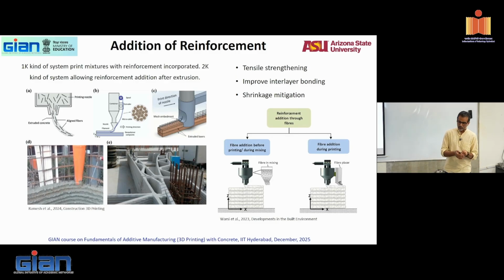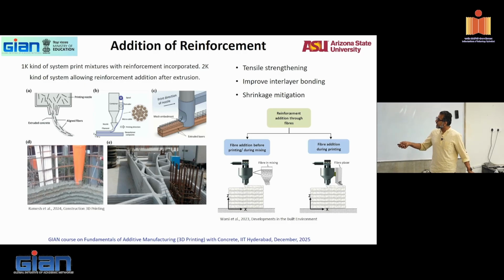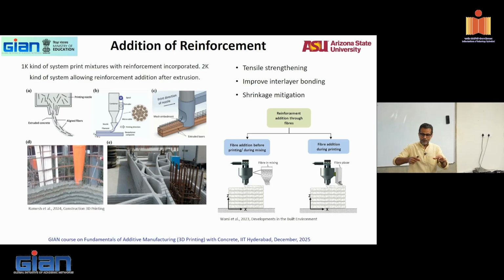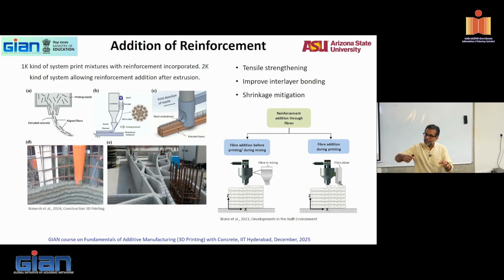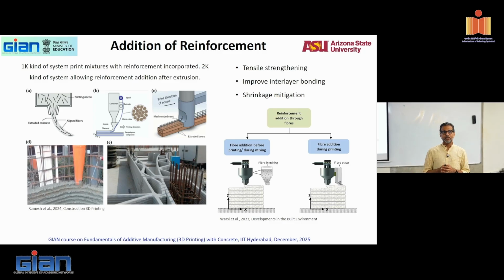And if you look at the random orientation of fibers added, as you print you see these fibers aligning along the direction of printing. The fibers will start to align along the direction of printing. So when you print a layer, you will have short fibers aligned along the direction of printing. Like we talked about yesterday, you're now getting an anisotropic composite material. The concrete does not have the same properties in all the different directions. Depending on the direction of testing, your properties are going to be different. Not much in the compressive property part with fibers, but with respect to tensile properties, flexural and tensile properties, which is something that we need to think about.